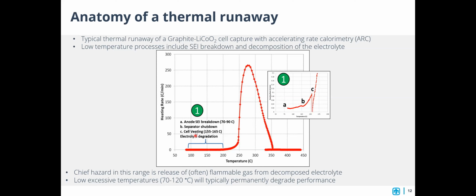First is the breakdown of the SEI. Again, that's what forms on your anode from the degradation of your electrolyte. That will happen at lower temperatures. Then, at about 130 C, your shutdown separator will close to try and prevent internal shorts. You'll then have cell venting, so your electrolyte will vaporize. And again, this can be an issue if there's an ignition source that can cause a flame to occur.